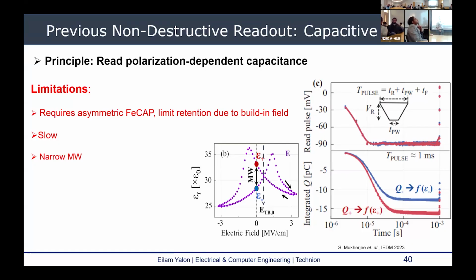What happens is that at zero bias, there is no difference in the capacitance, but in the work that Mukherjee did, they designed an asymmetric capacitor with a built-in field. So we just use different electrodes. Then with a built-in field, even at zero bias, there is a difference in the capacitance, and they read this difference in the capacitance to get a non-destructive readout. So that was a creative way, but it's fairly limited because the time to accumulate enough charge for this measurement was fairly long. It's about a millisecond. The memory window itself is very limited, very narrow. And because of the asymmetric structure, retention is also limited because there is a built-in field that always drives the state to no state.